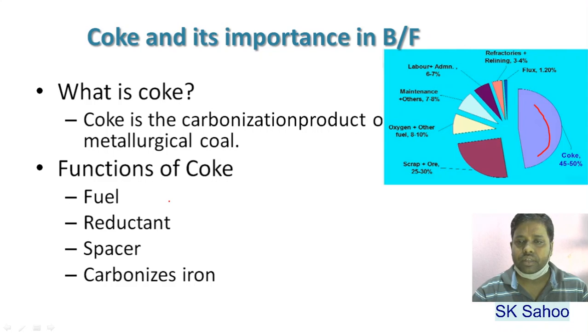What are the functions? First, as a fuel, it provides heat for endothermic reactions inside a blast furnace and also for melting of slag and metal. Secondly, it provides reductants. That means coke produces and regenerates reducing gases for reduction of iron oxides inside a blast furnace. And what is special? Coke provides an open permeable bed through which reducing gases pass upward and slag and metal trickle down to the hearth of the blast furnace. Besides this, carbon of coke is responsible for lowering the melting point of iron by carburizing it.